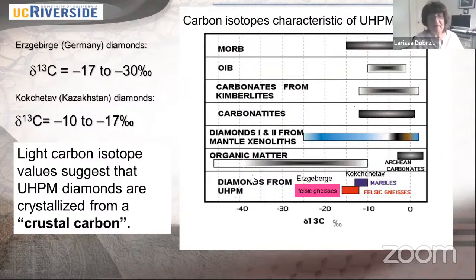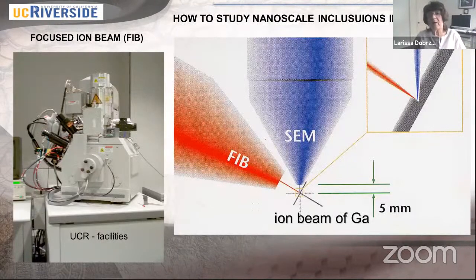What we see here: diamonds from ultra-high pressure terrain, Erzgebirge diamonds from Germany. They are characteristic of delta 13 carbon, minus 17 to minus 30. And Kokchetav Massif is a little bit heavier, but still from minus 10 to minus 17. So this allows us to conclude that this diamond's delta 13 provides evidence that this diamond crystallized from a crustal, light carbon. So now we want to study nanoscale inclusions in this diamond.